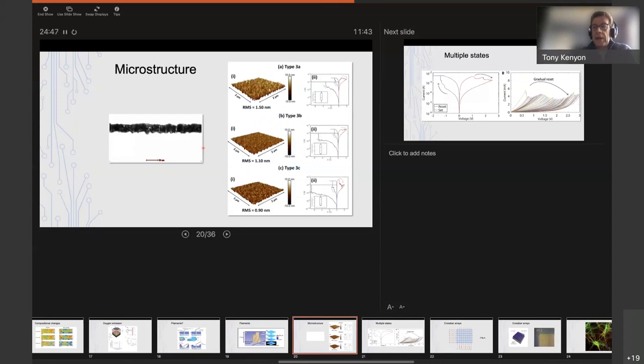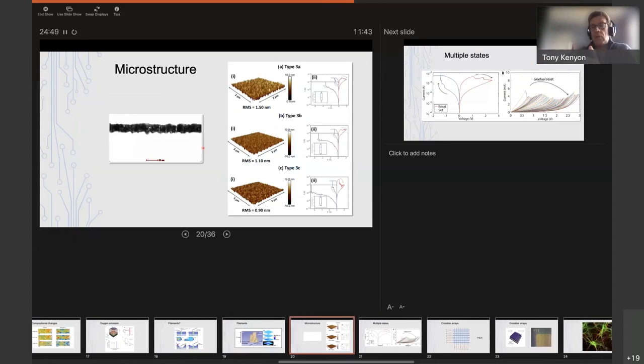Well, another way of looking at that is to take, again, a transmission electron microscope (TEM) image of this. So here what we've got is a thin layer, of the order of about 30 to 40 nanometers, of our silicon oxide. We're looking through it, the side of it. So there's a top electrode here, bottom electrode here. We have a very thin lamella, a very thin slice, which may be of the order of 50 to 100 nanometers thick. And we're looking through that with an electron beam.